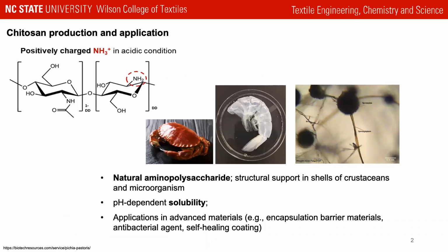Chitosan is a remarkably versatile carbohydrate polymer, which is produced at industrial scale by chemical hydrolysis of the N-acetylated parent polymer, chitin. Chitin is abundantly found in structural components in crustacean shell and microorganism cell wall. Because some N-deacetylation occurs through a natural biological process, and because chemical N-deacetylation can be incomplete, both chitin and chitosan are beta-1,4 linked copolymers of N-acetyl D-glucosamine and D-glucosamine, where the distinction between the polymers is empirically based on